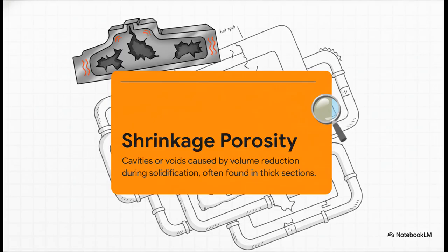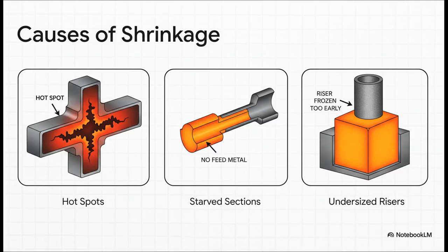You're going to find this sucker hiding out in the thickest sections of the part, or in hot spots where heat just can't get out. It's a dead giveaway that the metal was starving for more liquid as it was trying to solidify. So what causes this starvation? Well, it boils down to a few key culprits: poor solidification paths, risers that are too small, and those pesky hot spots. But really, it's all about one thing: shrinkage. As aluminum cools, it shrinks by about 6 to 8%. That's a lot. And if the thickest parts get cut off from a supply of fresh liquid metal while that's happening, they literally starve. And bam, you get these voids.